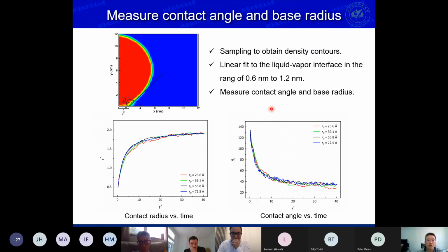So we use MD simulations. We can simulate different sizes of droplets using MD, and we measure the density contours. We do a linear fit to measure the contact angle. We can get the contact radius. Here, we simulate 4 different sizes of droplets. After normalization, you can see the temporal evolution of the contact radius and the dynamic contact angle actually collapse onto one figure.